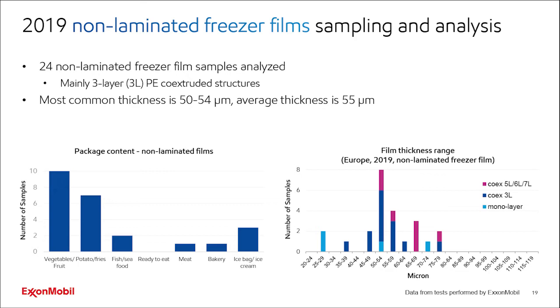First of all, 24 non-laminated samples were collected throughout Europe. And mainly, you can see in dark blue on the right-hand side plot that the most common structure is a co-extruded three-layer structure, right? As mentioned by Marcus, even with non-laminated freezer film structures, you can get several layers, all with PE. So that's the most common structure, in dark blue. And in terms of thickness, the most common thickness is in the range of 50 to 54 micron. And if we do the average calculation, we are at 55 on all the samples collected for non-laminated freezer film, right? And as mentioned a bit before by Marcus, you can see we collected lots of raw types of food like vegetables or fruit, which are typically packed in non-laminated freezer films.